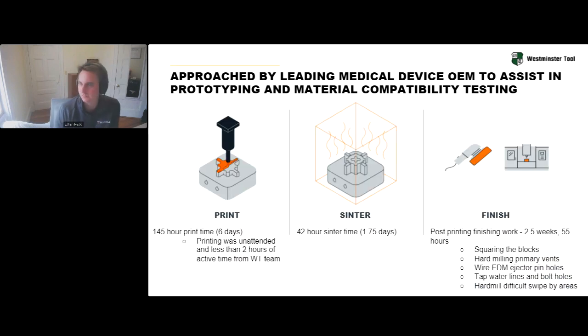It was 2 relatively larger inserts, so they printed these in about 6 days. What's really important here, though, is that it was only 2 hours of their actual team's time to get this started, to get the machine set up and running. It's going to print, hopefully, while you're sitting on the beach on the weekends, and it's back at the shop working. They put it in the furnace for about a day and a half, so they had these inserts completed in about a week. Then they did about 2.5 weeks of finishing work on these inserts.